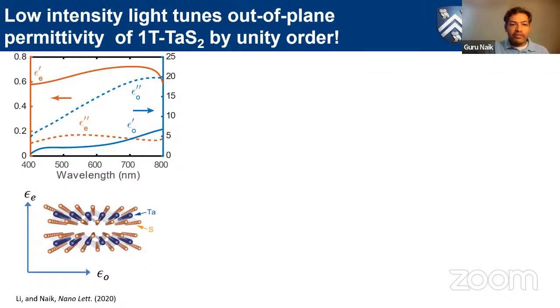And we have, in fact, a Fourier plane imaging microscope, which means we can take angle resolved reflectance and transmittance from small area samples. From that, we can extract the optical constants. So we did extract optical constants at very low illumination intensity. All I'm talking about is incoherent white light illumination, no coherent illumination like laser illumination here, just white light from a tungsten halogen lamp. Here the intensity was about 10 milliwatt per centimeter squared, and we extract the optical constants.